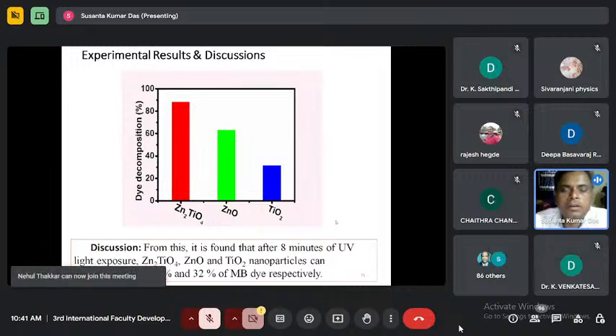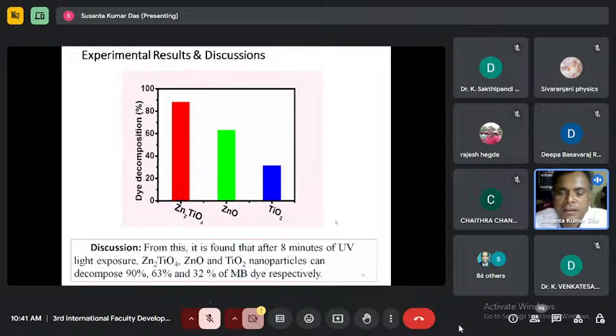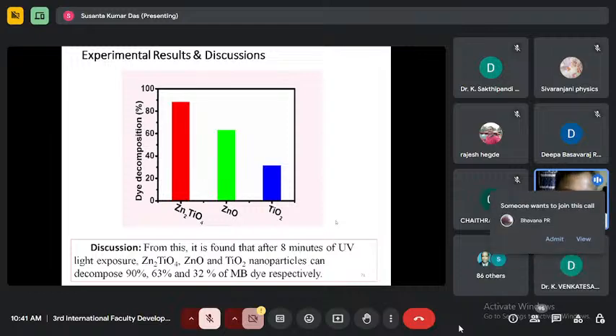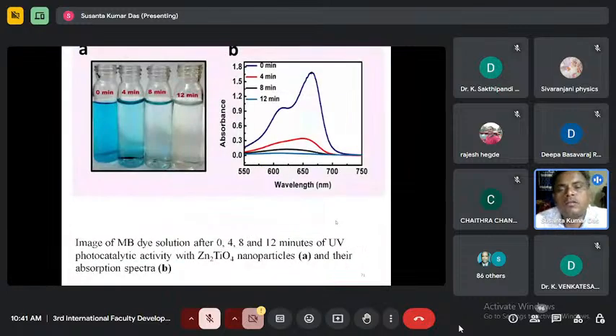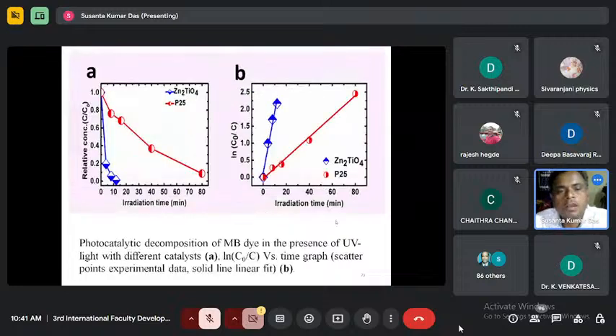Now, when we did the experiment with UV light, we found that for both of the constituents, the compound was showing much higher activity. We tried to find out the reason behind this, and we found that one of the biggest reasons is the increase of the lifetime of the excited carriers. Generally, the lifetime increases, so the electron-hole pair stays separated for a much longer time. So the reaction takes place for a longer time, and it shows faster, meaning better, results. Here we have shown this result, you can see, and also we made a comparison with P25.